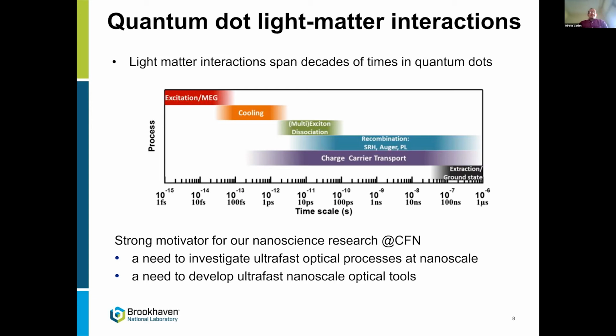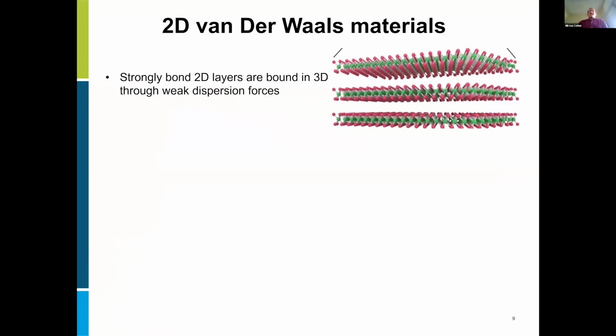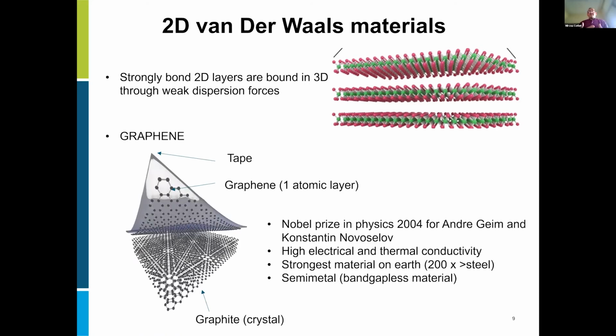Quantum dots are extremely nice nanoparticles. We have been studying them for over a decade. We're also interested in two-dimensional materials, in particular two-dimensional van der Waals materials. These are materials where atoms are strongly bonded in plane, like chemical bonds, but adjacent planes are stuck together through weak dispersion forces, like van der Waals forces. So that means we can use mechanical exfoliation or mechanical methods to separate layers from each other. And this has been done, for example, for graphene. So we have graphite here, we use Scotch tape, and we can isolate a single layer of graphene,